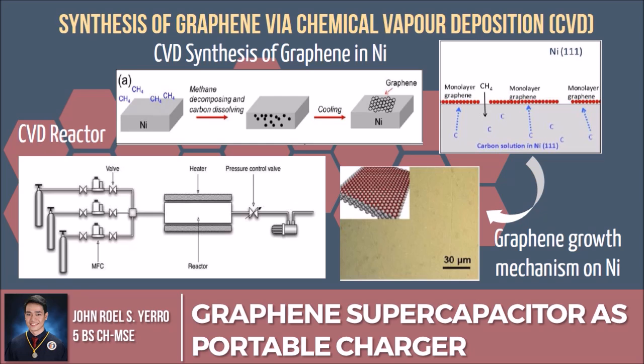They synthesized graphene using chemical vapor deposition, or CVD. During the CVD process, gas species are fed into the reactor and pass through the hot zone where hydrocarbon precursors decompose to carbon radicals at the metal substrate surface and then form single layer and few layers of graphene. During the reaction, the metal substrate not only works as a catalyst to lower the energy barrier of the reaction, but also determines the graphene deposition mechanism, which ultimately affects the quality of graphene.